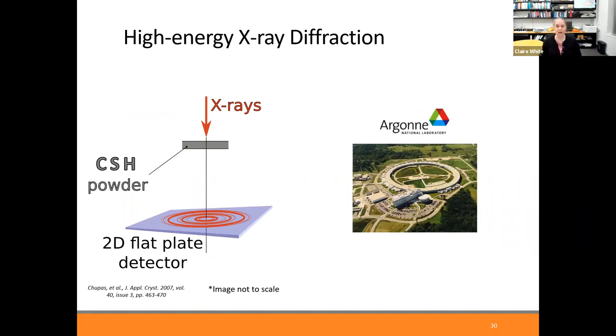And so to do this technique, we went to a synchrotron. We specifically went to Argonne National Lab, the Advanced Photon Source. And you can think of it as conventional X-ray diffraction, but on steroids. I don't know if that's a good term. What it is, is that you're using the high brilliance of the X-rays from the synchrotron to scatter from your sample, which means that you're getting a lot more X-rays being detected, which leads to higher resolution data.